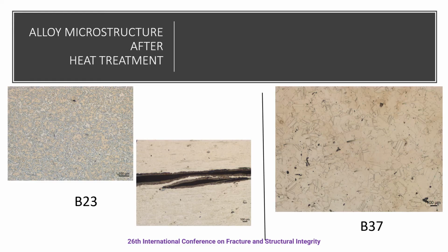In order to study this change in behavior after heat treatment, the microstructure of both the alloys was again analyzed. While B37 has the austenitic structure as before with visible twins, it is B23 that has completely changed its microstructure. From the picture in the center, it can be noticed that B23 has also formed delamination layers after heat treatment.